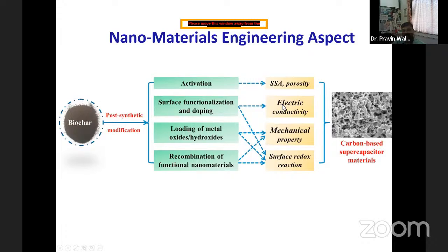Another important thing is your electrical conductivity. You need to have good electrical conductivity of your electrode material. And how can someone tune that electrical conductivity? Just by doping your material. Let's say, for example, you have one material, and if you dope various metals or you functionalize certain metals to your material, then definitely you will see the electrical conductivity get tuned. And second, because of that functionalization or presence of external atoms, those will help you to have redox active sites, right? And therefore your surface redox reaction will be enhanced because of the dopants as well as functional atoms. So these two properties directly get modified just by doping and surface functionalization of the given material. We'll see some examples of this surface functionalization or doping in the next slides.